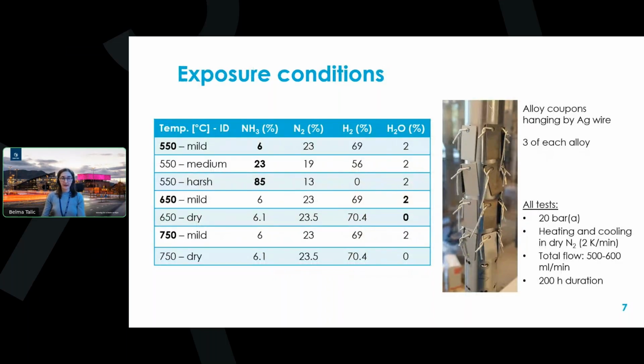So the different candidate alloys that were studied were all acquired in sheet form and cut into coupons that you can see pictured here. They were mounted inside of the reactor using silver wire. For the testing, we had at least 3 different coupons of each alloy type that were arranged vertically within the reactor in order to account for any variations with respect to position.